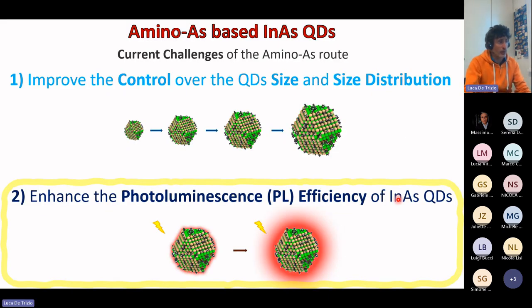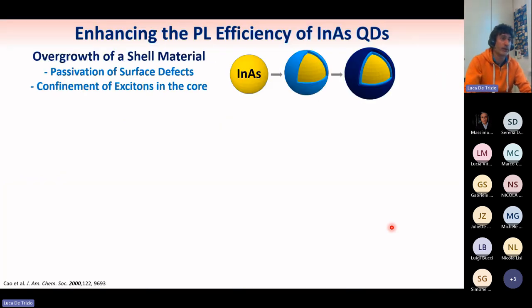So most of our efforts were devoted to the second point, which is to enhance the photoluminescence efficiency of indium arsenide quantum dots. And what people typically do to enhance the PL of these indium arsenide dots, or in general of semiconductor quantum dots, is to passivate the surface with a shell material. So typically what we do is to cover indium arsenide or other dots with a shell material that is able to passivate the surface defects and to confine the exciton, meaning boosting the recombination of excitons in the core region, eventually getting what we call core shell materials that you see here.